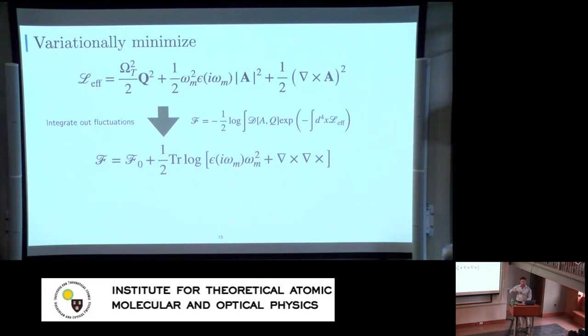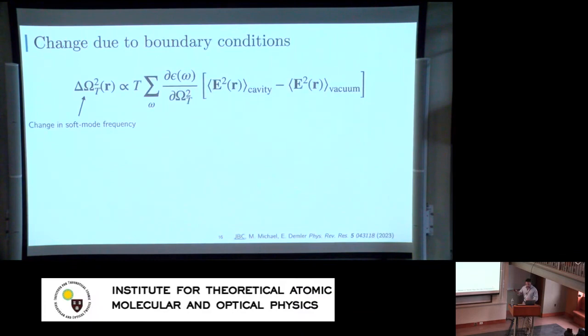That's just to say that there's a contribution to the free energy, due to the vacuum fluctuations in this variable dielectric, and you minimize, essentially find what is the dielectric. What's important is because of this magnetic induction term, it's actually sensitive, it's a non-local effect. It's sensitive to boundary conditions, this is just saying photons have dispersion, and if you put a mirror, then they will bounce off the mirror, and you will suppress electric field fluctuations near the mirror.